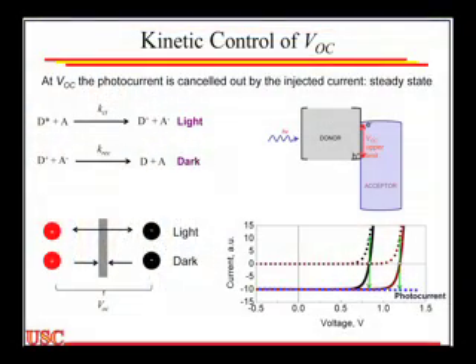The open circuit voltage is when the current produced by the light reaction, which is charge separation from the excited donor, is exactly balanced by the current injected at the contacts. So you can think of this as my light reaction. This is what happens if I turn the device off and run the bias in the forward direction so that the current exactly compensates or wipes out the current that's there. And so it's the balancing of those two rates. When the rate of current production equals the rate of current annihilation, we're at the open circuit.